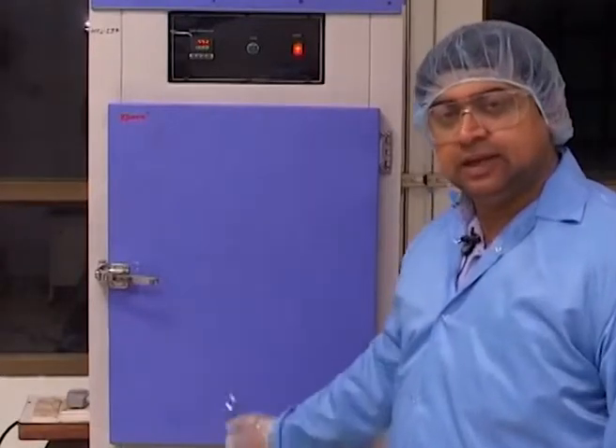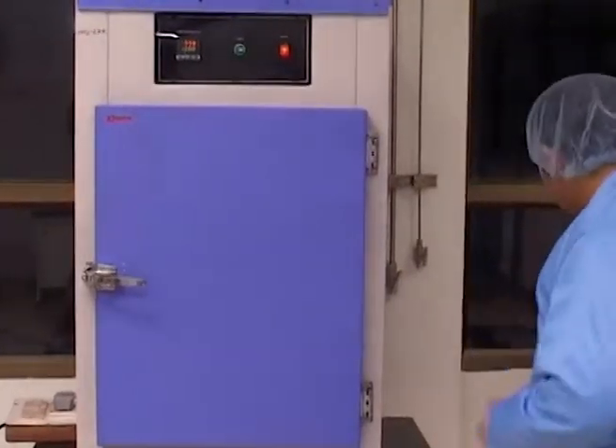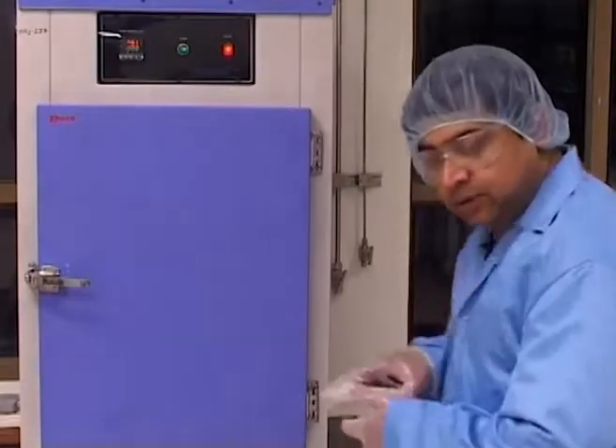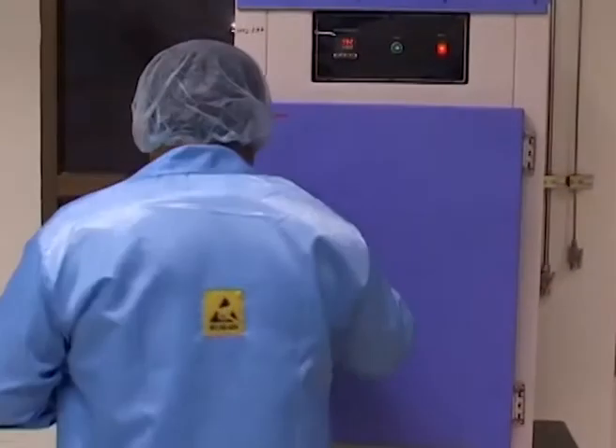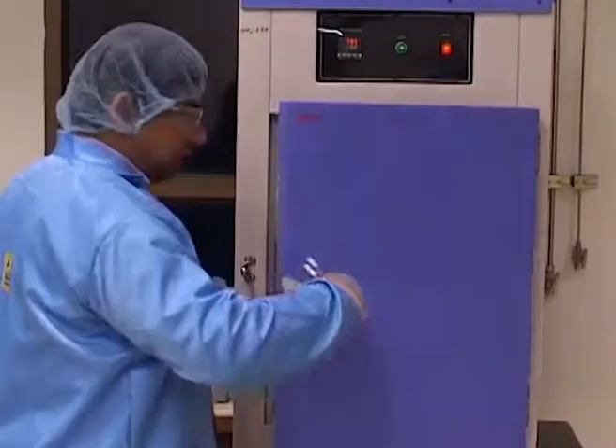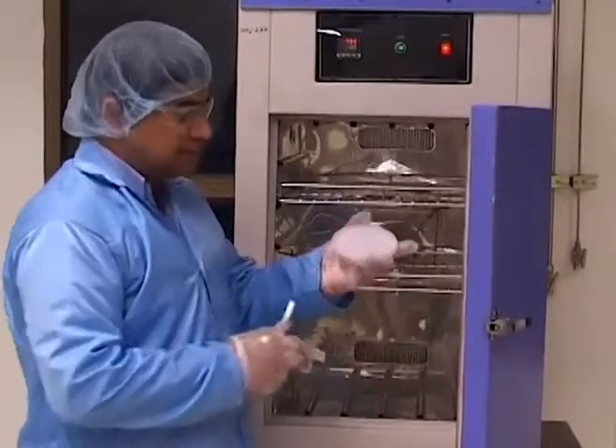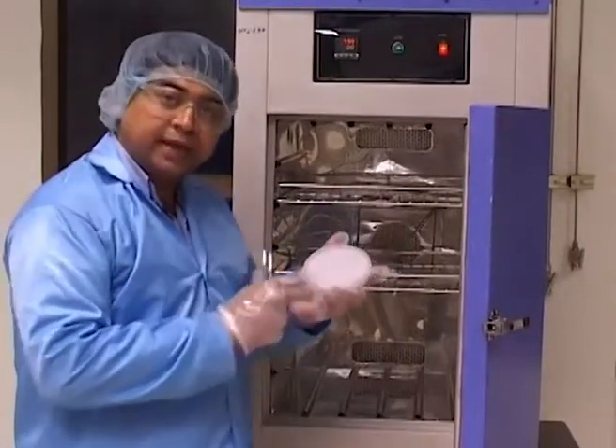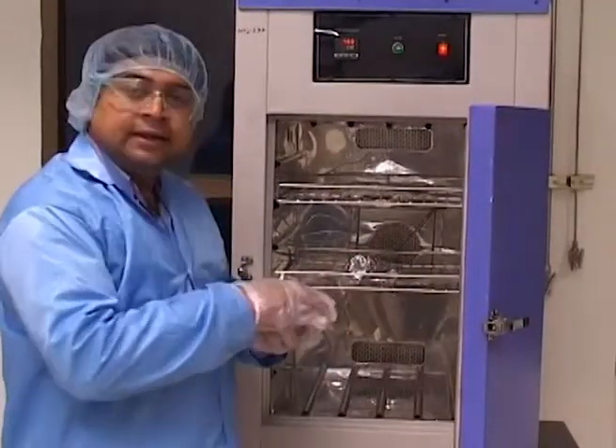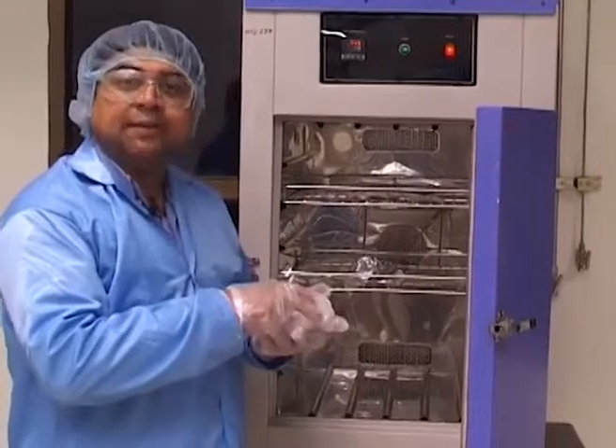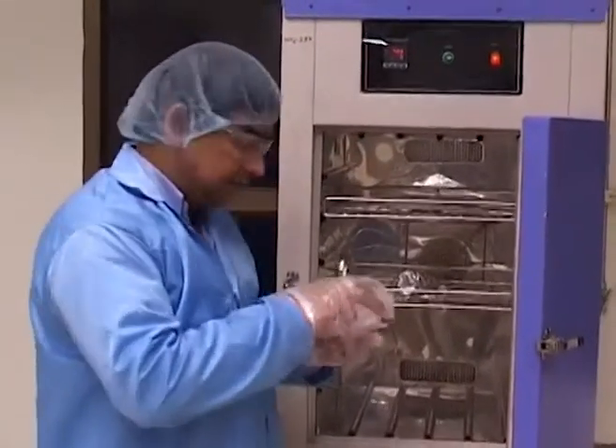So we keep the wafer in the oven for dehydration for about 10 to 15 minutes at about 99 to 100 degrees Celsius. The next step is to unload the wafer and start doing what we call spin coating of the photoresist. So what I am going to do is just unload it and carry it back again. Please note that we are using the same wafer box for carrying the wafer, so that it does not get contaminated while going between operating stations.